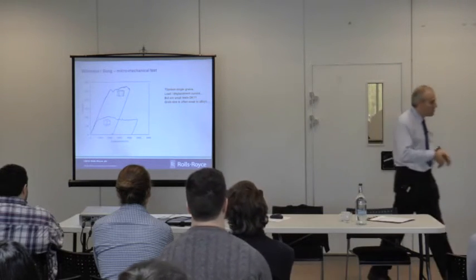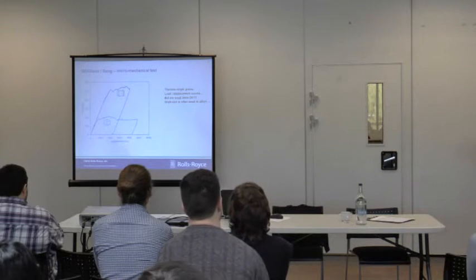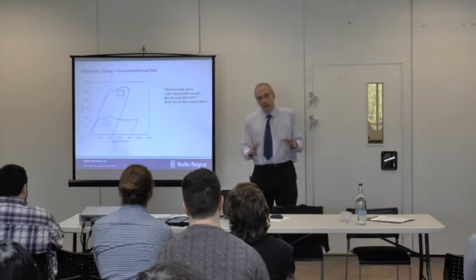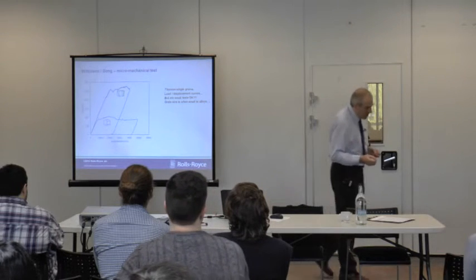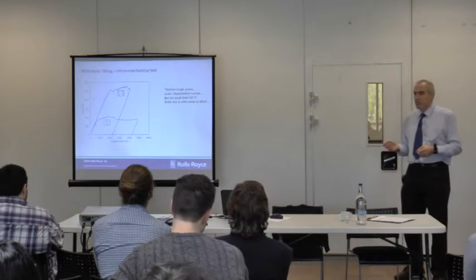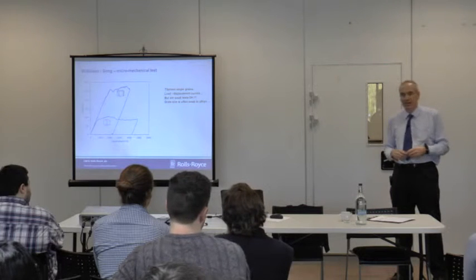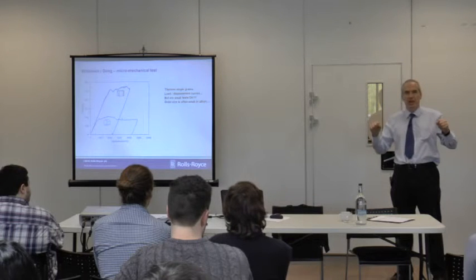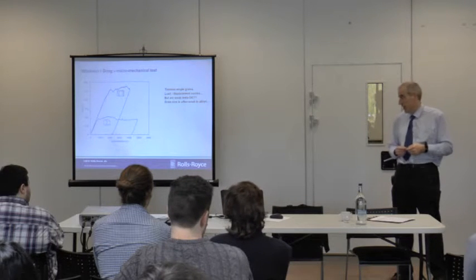So we're on to real things now. One of the incredible things that's been going on is that modelling and experimental techniques in the last decade have become unrecognisable, and it's accelerating. The majority of materials derive their strength from length scale, not from chemistry per se. If I take an alloy and throw in elements, you'll get some strength contribution from solid solution or interstitial strengthening, which is just the atoms sat there interfering with the dislocations going past. But the bulk of the strengthening actually arrives from length scale.